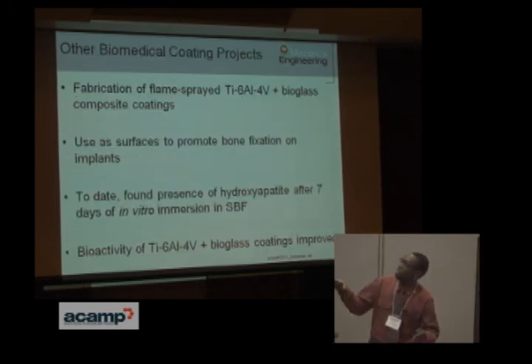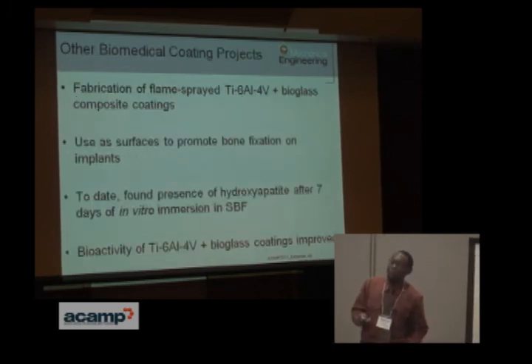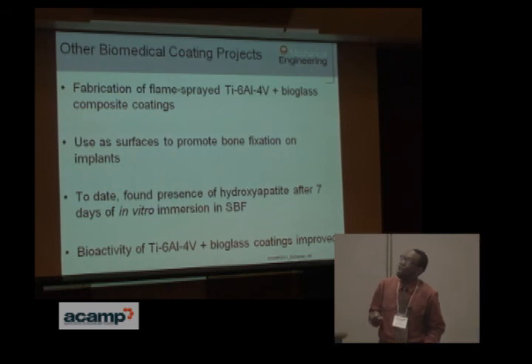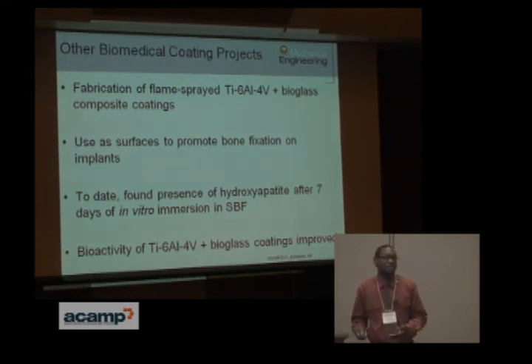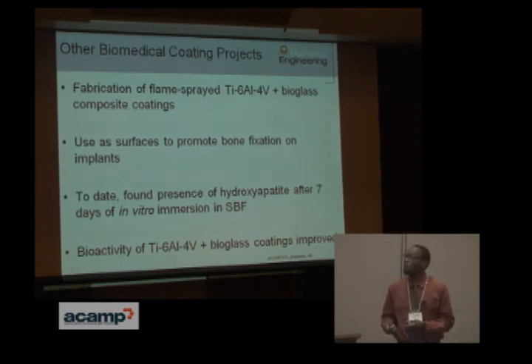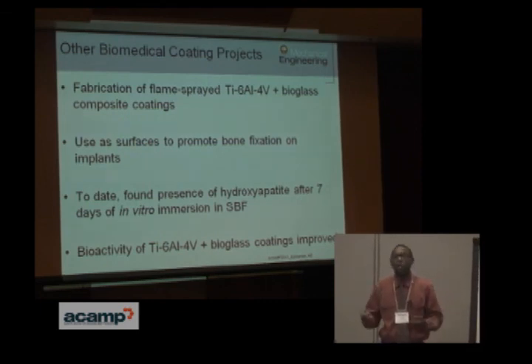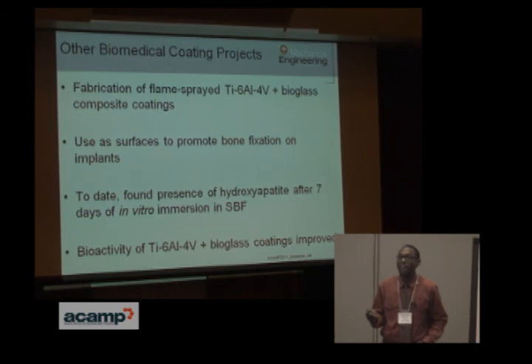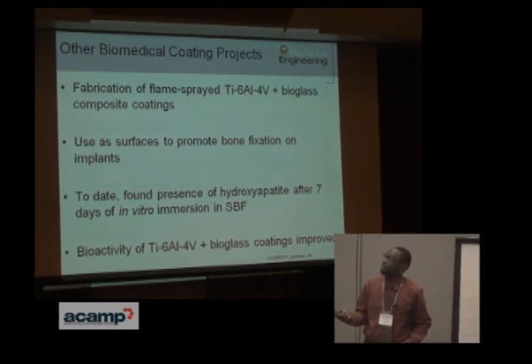And if I can just add very quickly, we do have other biomedical coating projects going on. One of them involves the development of a flame-sprayed titanium alloy bioglass composite coating for use as an implant coating to promote bone fixation in implants and to promote the development of hydroxyapatite, which is indicative of biomineralization on surfaces. So we've been getting some very positive results, and again, we're always open to discussion and to potential collaboration in this area also.